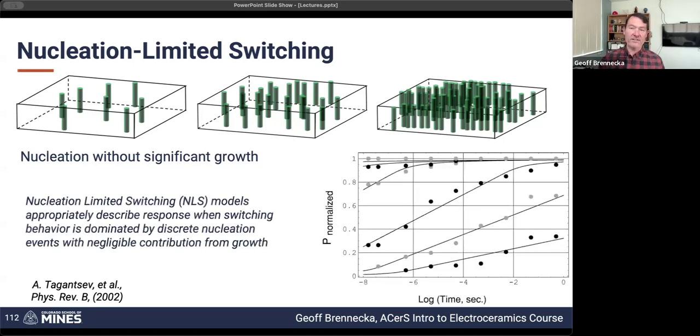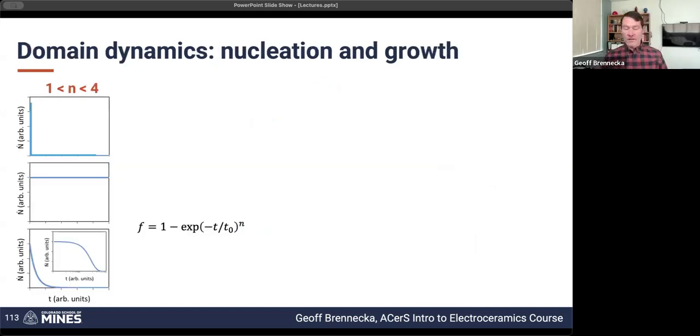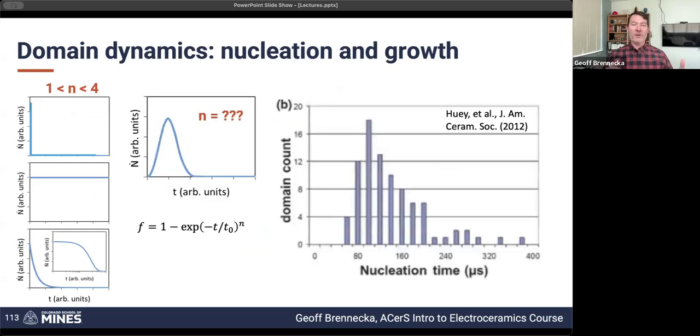And so this is actually seen in a lot of ferroelectric thin films in particular, where it's pretty easy to start a nucleus and get it to grow, but the cost of expanding the domain walls laterally is expensive. And so from this, you can actually look at what happens if you start off with all of your nuclei at the beginning and then there's no additional nucleation, or if there's continuous nucleation happening as you go, or even this Jacobs version where you start with a bunch of nuclei and then you're adding more, but the rate of adding more decreases.